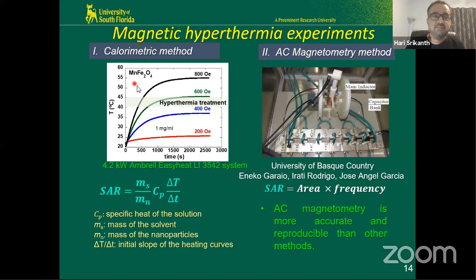And you can see for these manganese ferrite nanoparticles of about 20 nanometers average size, we can see that the hyperthermia treatment is effective for about 500 Oersted applied AC field at a frequency of 325 kilohertz. Okay. If you apply a large field, you will overshoot this window, overheat it, not needed. And of course, if you don't apply the right field, you'll never come to this hyperthermia treatment window. Okay. The saturation is because of the thermal equilibrium achieved between the particles and the surrounding medium, in this case, cells or any other environment surrounding that. That depends on the latent heat and the specific heat of these particles.